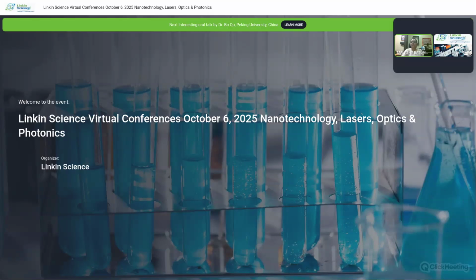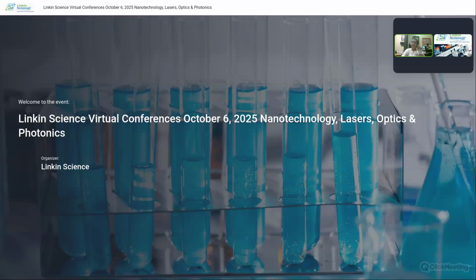With the use of zinc oxide, it helps to enhance plasmonic field interaction, and graphene helps to improve biomolecule affinity. The method that we use is TMM, which is the transfer matrix method, to model the reflectance and determine the resonance angle. With that, I conclude my presentation.